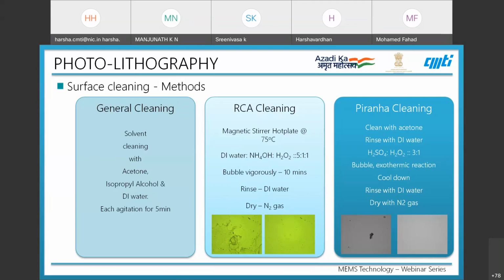Moving to Piranha cleaning, we need to clean it with acetone, rinse with DI water, and mix H2SO4 to H2O2 solution in a 3:1 ratio, allowing it for exothermic reaction. Then the solution has to be allowed to cool down, since there would be a rise in temperature. Then rinse it with DI water and dry it with N2 gas.